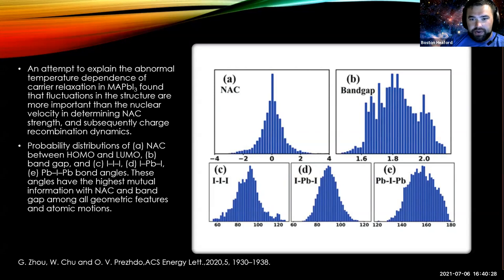And this is a plot, an attempt to explain an abnormal temperature dependence of carrier relaxation in methylammonium lead iodide. They found that the fluctuations in the structure are more important than the nuclear velocities in determining non-adiabatic coupling strength. So even though non-adiabatic coupling strength is directly dependent on nuclear velocities, it's the fluctuations in the structure that actually influence it more than nuclear velocities do, which was an interesting find in the paper.